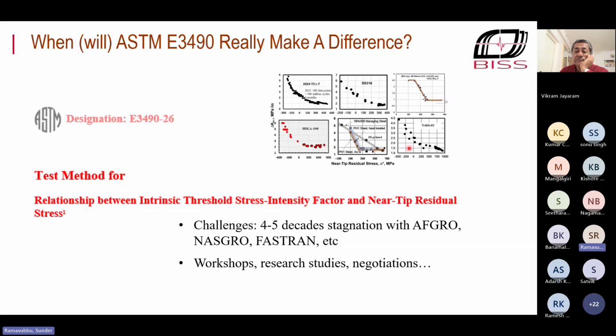The other thing, you being a researcher, let me pose this possibility to you and your whiz kids around you. You have this relationship. It's between ΔK threshold intrinsic, which is the fatigue limit for the crack tip, and a computed near tip residual stress, right? This near tip residual stress, you can convert it into mean stress. It's just an analytical conversion. Would you then think about converting this into the Goodman diagram for the material? Don't you think that possibility exists? Then you would have a new standard to convert this property into the Goodman diagram. How about that?